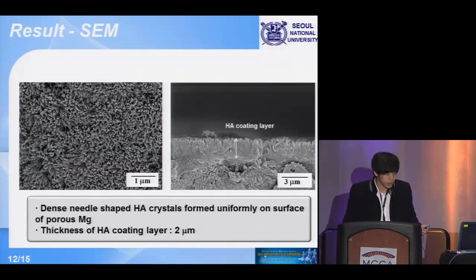And this is the SEM image of the hydroxyapatite coating. And as we mentioned before, you can see the needle-shaped hydroxyapatite uniformly on the surface of the porous magnesium, as Hiromoto mentioned. And the coating layer was about 2 micrometers.